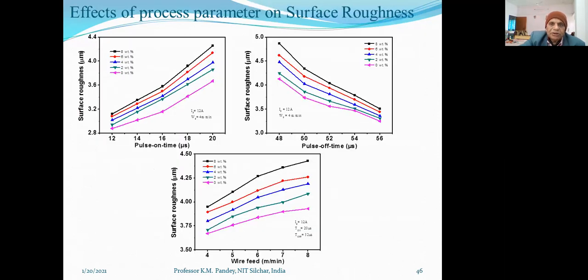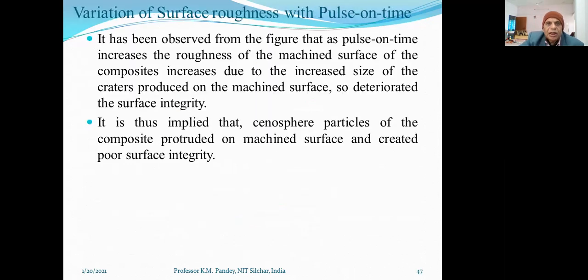Then the effect of process parameters on surface roughness. The graph is self-explanatory, and here we can see that as pulse on time increases, the surface roughness of the machined surface of the composite increases due to the increased size of the crater. It is thus implied that the cenosphere particles of this composite protruded on the machined surface and created poor surface integrity.